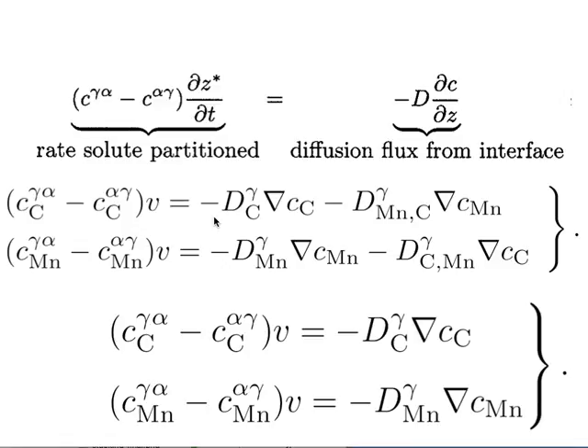Okay, so if I go back to this slide, I have a choice of tie lines. If I can pick a tie line which reduces the gradient of carbon to compensate for its high diffusivity, then the two equations could be satisfied simultaneously. Now, how can we pick a tie line which ensures that the gradient of carbon is reduced? Suppose that we can choose a tie line which makes the concentration gradient of carbon in the austenite flat. Okay, so this is C bar, this is C gamma alpha, and C alpha gamma. And what we want is this gradient to become as flat as possible.